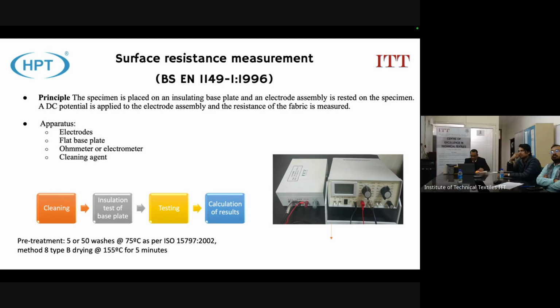based on their guidance. And for textiles, one thing is very important. If you are not using a disposable garment, the samples must be washed 5 times to 50 times before testing. This is something I'm seeing a lot of cheating happening. We have a lot of certificates where samples are not washed and it's just tested and says, oh, it passes the test. But what happens when you wash it 5 times or 10 times or 50 times? Because most of these workwears will be used and washed multiple times before being discarded.